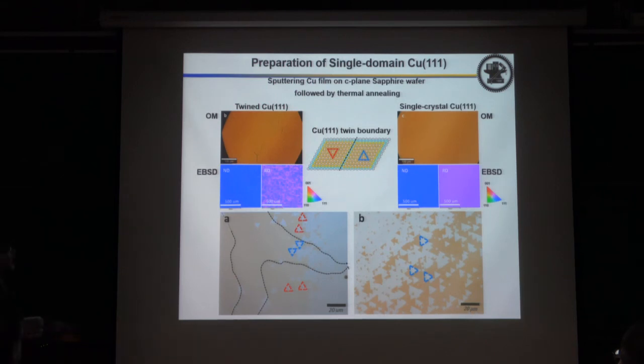Good question. Actually, if you grow the material on oxide, for example on sapphire, and you tune the growth condition to grow monolayer, typically you cannot grow the second layer, because once you form a very good monolayer on sapphire, it is very difficult to see the second layer on top, because they don't have dangling bonds. But they can very easily sit on a sulfide surface, because the sulfide surface has some dangling bonds. They will trap the atom. This situation is similar to graphene: no dangling bond, no surface bond, so it's hard to sit any other atom on top to form another layer. But if your growth condition is poor, and your CVD is very dirty, you easily form different kinds of layers.